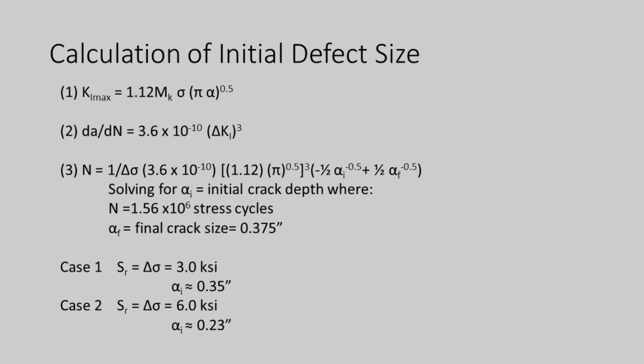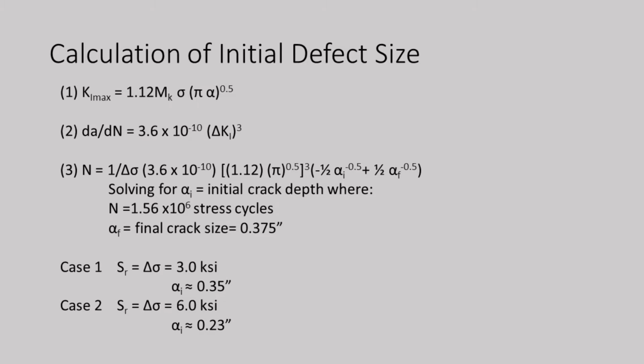Here's the fracture mechanics equation. It relates a value called the critical stress intensity, K1 max in this case. You have stress there, you got crack depth there, there's some shape factors, I believe. And this is a crack growth equation that was derived by John Barsom and Stan Rolfe, who had basically come up with the fracture control plan criteria that AASHTO still uses today.